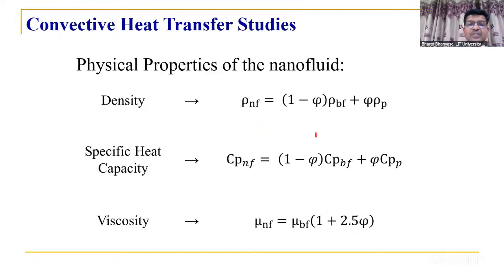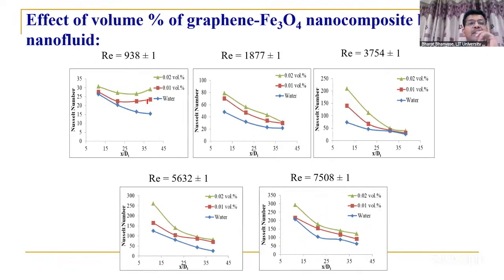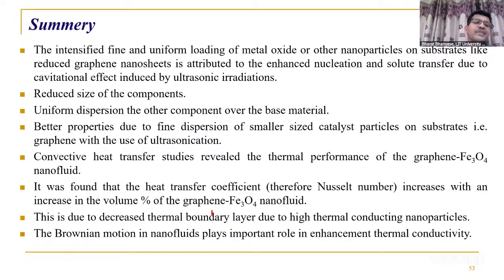At different concentrations of the nanofluid and different Reynolds numbers, we used different correlations, and this is what we got for Fe3O4, graphene Fe3O4 nanocomposite. We observe that Nusselt number increased with the addition of nanocomposite, for different Reynolds numbers and different flow conditions, and this increase was observed in every case.